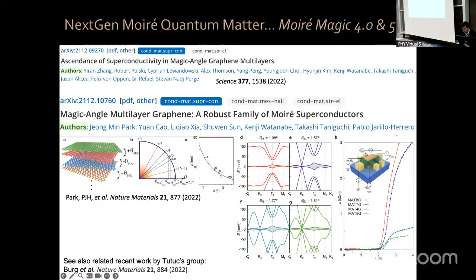As you can see here, for bilayer, tri-layer, 4-layer, 5 layers, TC increases, but only by a little bit. Turns out the magic angles predicted for 2, 3, 4, 5 layers are slightly different.